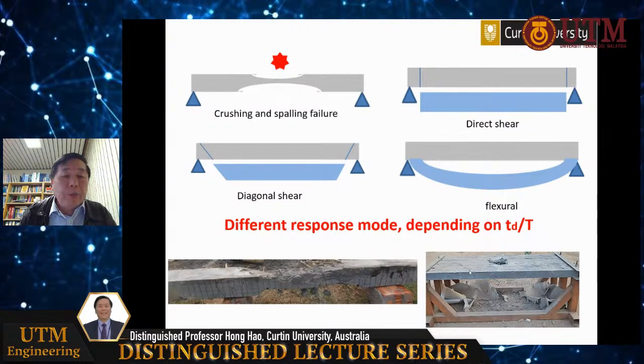Now consider blasting on a simply supported beam. It very much depends on how close the explosion blasting center is. You might get concrete crushing and spalling, with no deformation or structural response. It's just localized damage caused by stress wave. Or you can get direct shear or diagonal shear, when the blast loading is further away. That means the loading rate is not that fast, so you get the traditional fracture-governed type of response, equivalent to static loading.